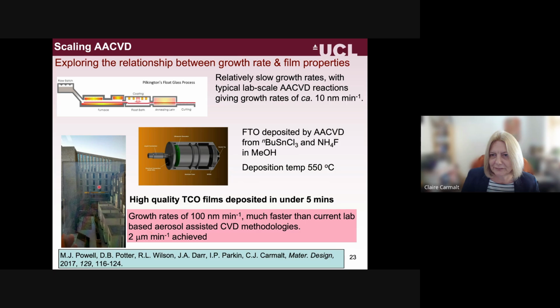And this just shows you the film. It's our FTO film deposited on glass. We're looking through our film out of the window to the building opposite our building. So a very nice transparent film, and it did have the resistivity that's needed.